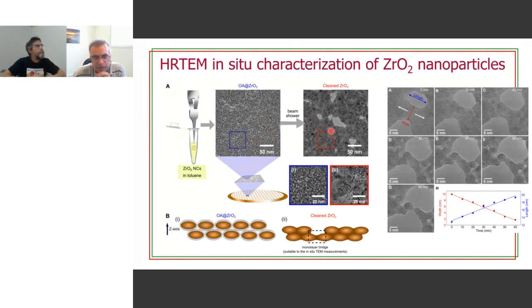And when you do that, under the electron beam shower of the microscope, you remove this organic surrounding material, and in the end, you form a very thin layer, one or two monolayers of zirconium dioxide nanoparticles, and they are thin enough that you can visualize those at the TEM, right? So these are snapshots in the evolution of thermal treatment of these nanoparticles. I think this is actually room temperature, but what happens in general is that these nanoparticles will sinter.